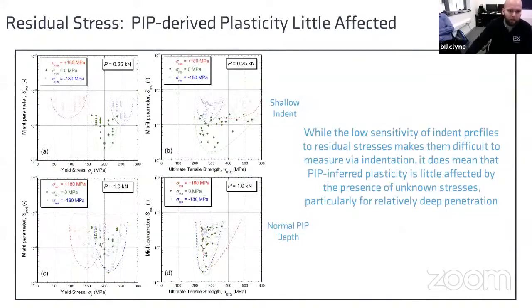So what's the outcome of this if we just ignore residual stress and only try and infer the plasticity parameters? So in our model, we keep the residual stress set to 0, and then we try and infer with different sets of indents where residual stress had been present. So we can see at the low loads, the effect on the yield stress, so the yield stress in this case is 200, is reasonable at these lower depths. So we can see it drops down to 100 or up to 250 when we have residual stresses, which are 180 megapascals, so quite high in this case.